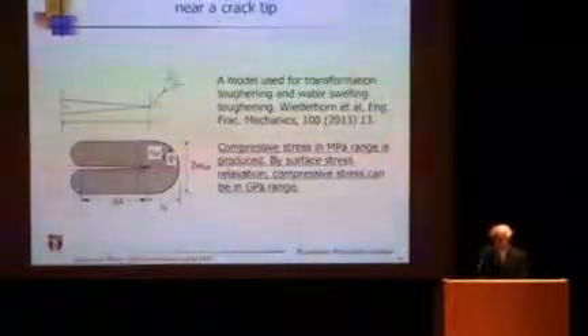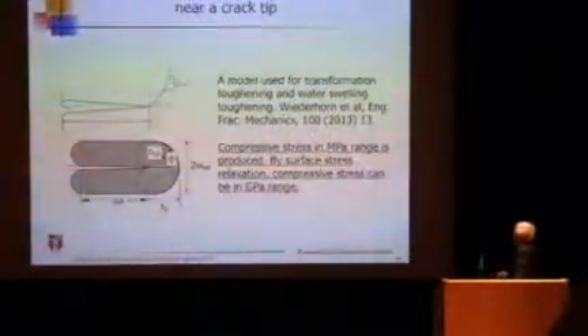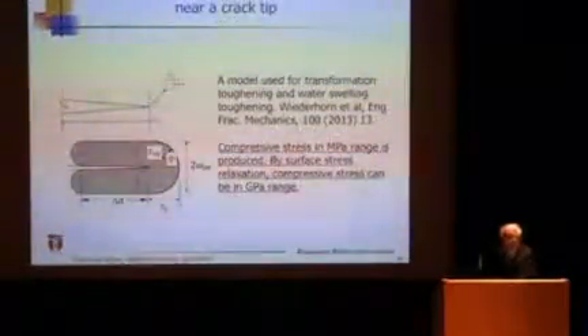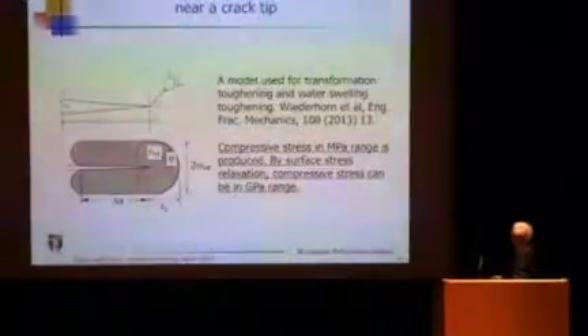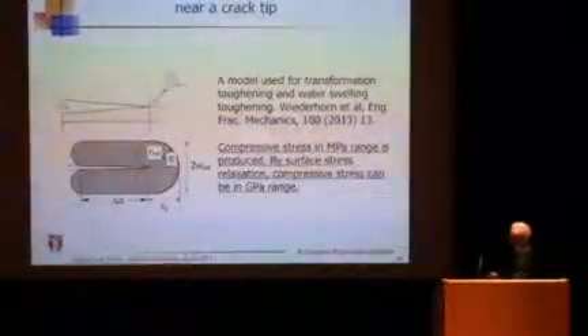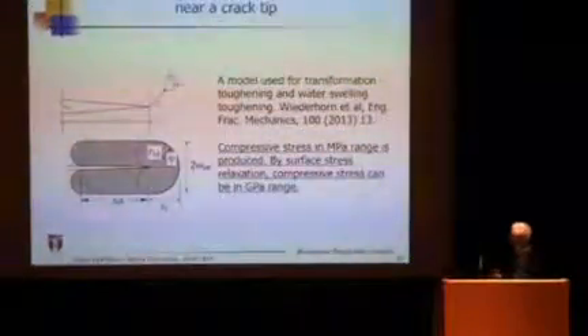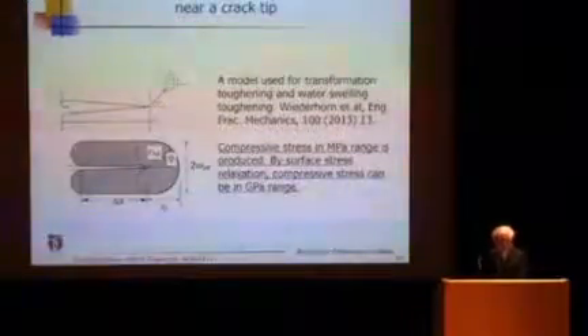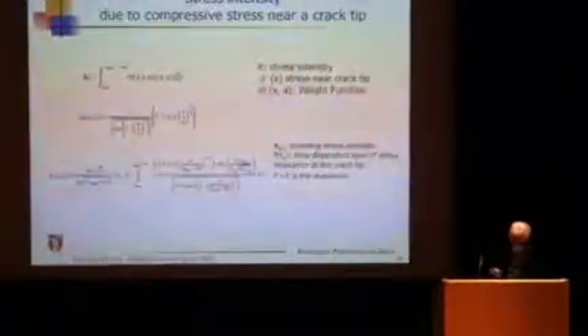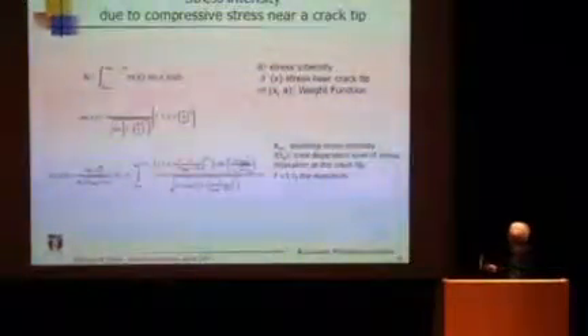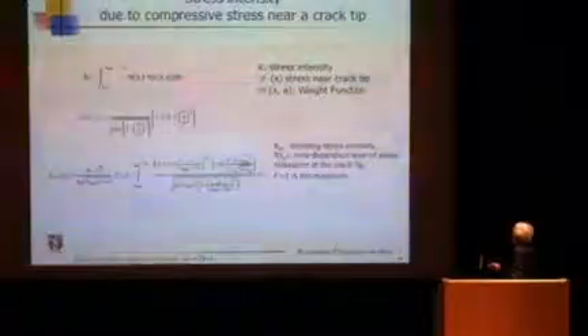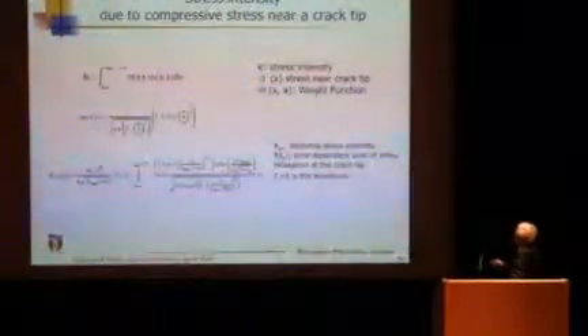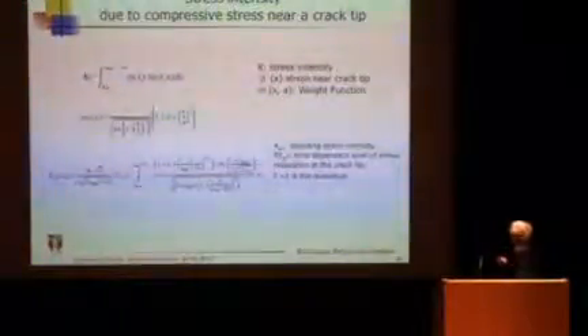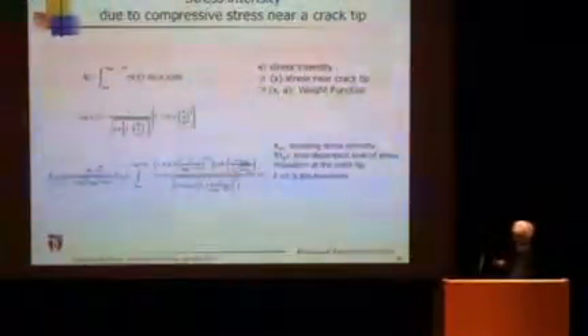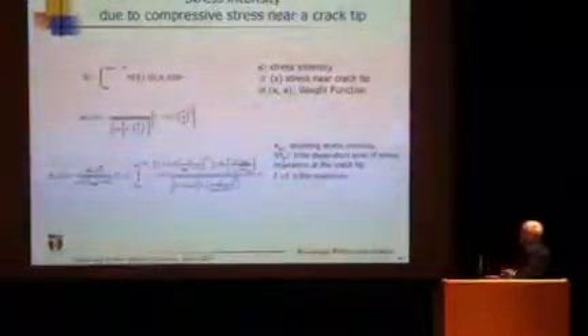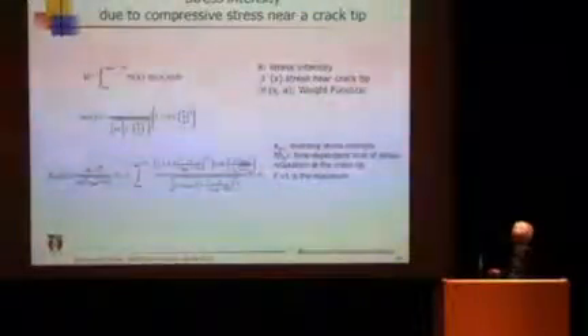And that idea has been used in some other materials, such as transformation toughening of ceramics. And more recently, Wiederhorn thought water diffusion itself is making an expanded swelling region that mitigates the applied tensile stress. So we use a similar mathematical formula. Normally, in general, stress intensity is a function of applied local stress and a weight function. This is the mechanical engineer's realm, so I have to accept what they say. The weight function is given as long as you have a particular shape of the crack tip.